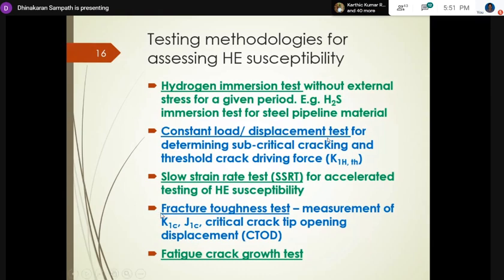So, and then the most concrete parameter to get is fracture toughness test. Again, this is also a very valuable test for life prediction. And fracture toughness, as I told, is the ability to evaluate the ability of the material to undergo unstable cracking in the presence of hydrogen. There are several fracture parameters like K1C, J1C, and critical crack tip opening displacement. They are all standardized and more or less considered as a property of the material, but it's not. They are also subject to a lot of variability.